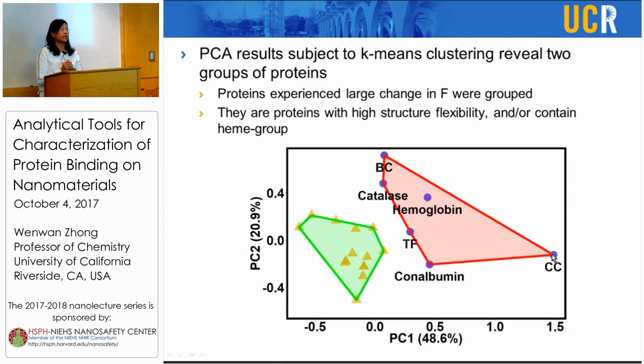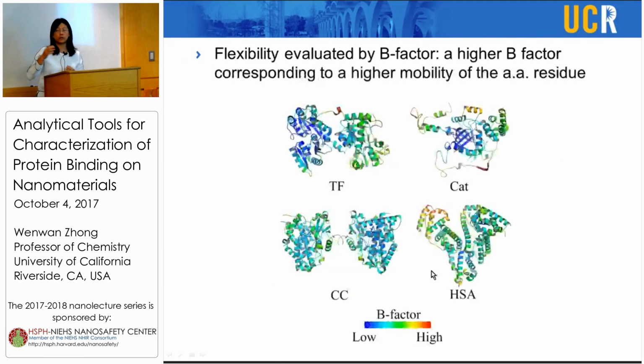And transferrin and conalbumin actually have very high similarity in their structure. And for transferrin and also hemoglobin, they could form oligomers like tetramers. So high structural flexibility as well as heme-containing proteins show high fluorescence change, which could potentially be due to conformational change, right?